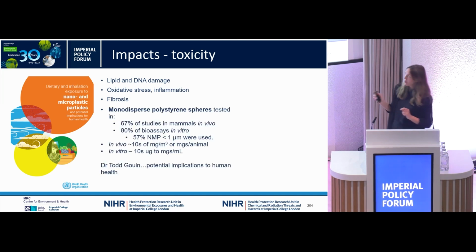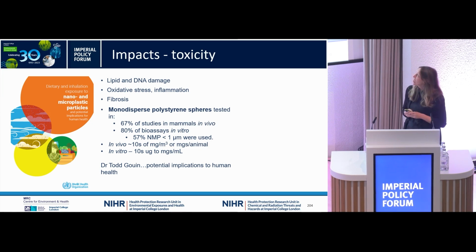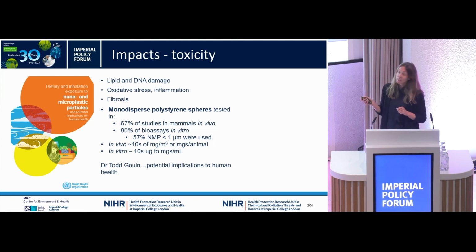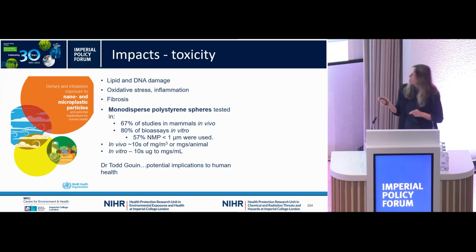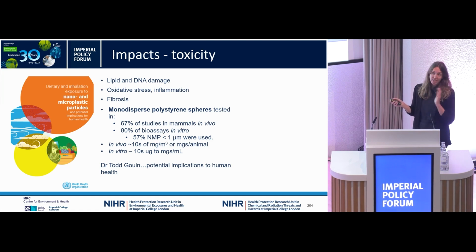But it's really important to highlight that the majority of these studies use monodispersed polystyrene spheres. So this was in 67% of the in vivo studies and 80% of the in vitro studies. And over 50% of those in vitro studies also tested nanoplastics smaller than a micron in size.